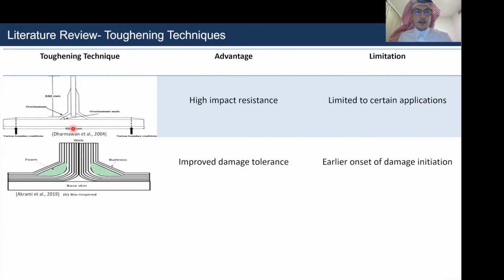Second mechanism is by employing bio-inspired designs. These designs are usually inspired from the animal or the bird bones, and this is practically done by inserting a foam in the region between the plies of the stiffener. And this insertion of foam, or this bio-inspired design, provides an improved damage tolerance. However, this again has a limitation, and this limitation here is the onset of damage initiation earlier.